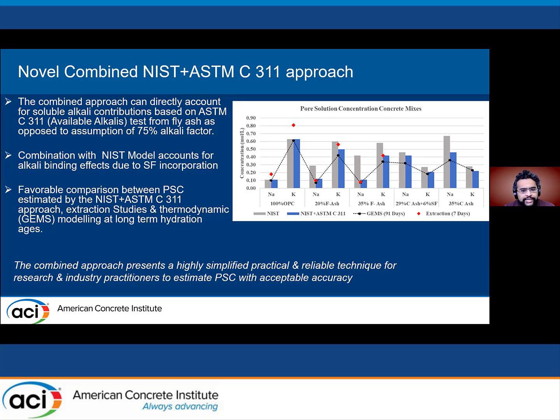So the results from the NIST and the NIST plus ASTM C311 are presented in the graph there. The blue bars represent the NIST plus ASTM C311 versus the NIST in the gray. There was also a thermodynamic GEMS model that was developed for these compositions of fly ashes and the replacement levels, and the values are shown with the lines and have been compared to the extraction values. So for the cement, of course, since there is no SCM, both the NIST and the combined NIST and ASTM C311 approach perform pretty well.